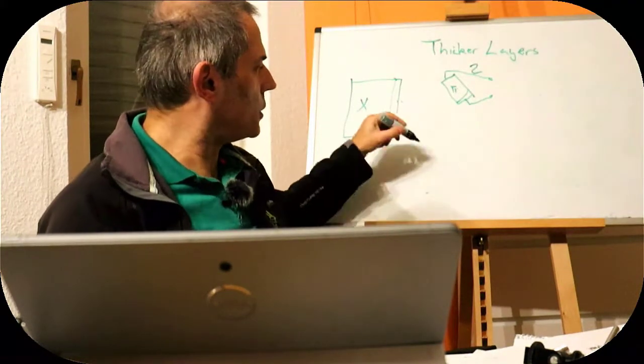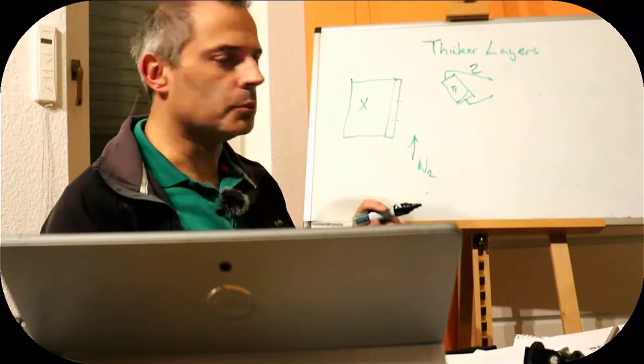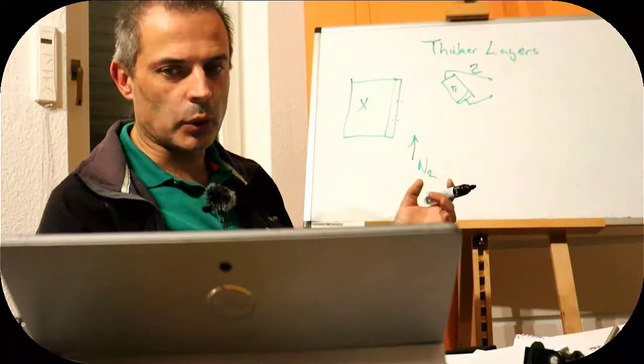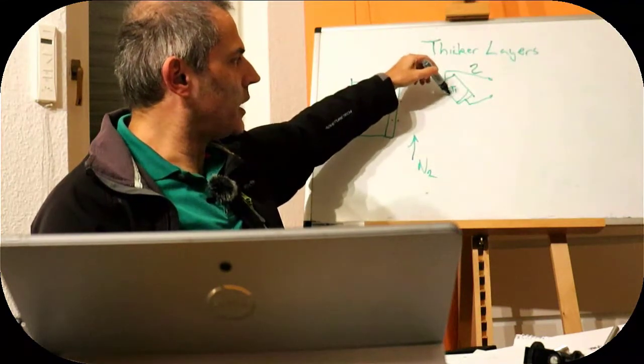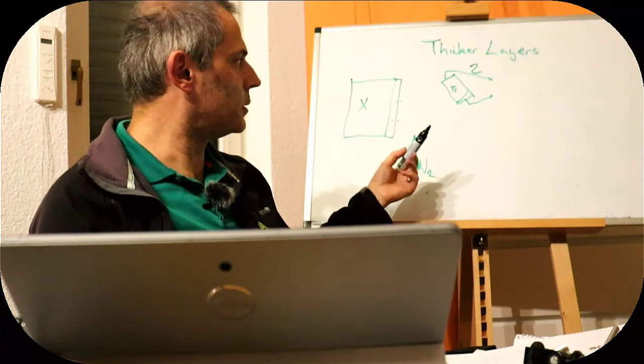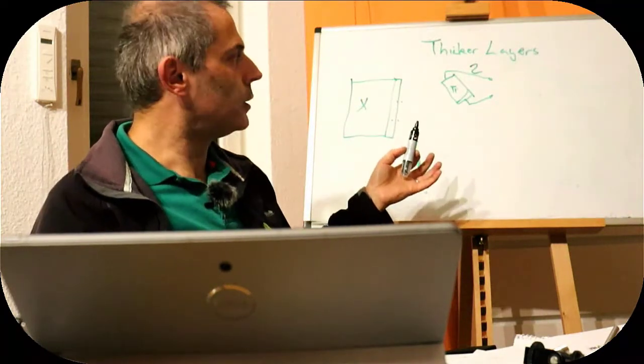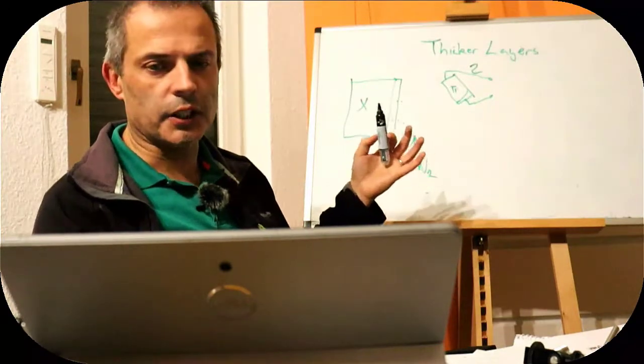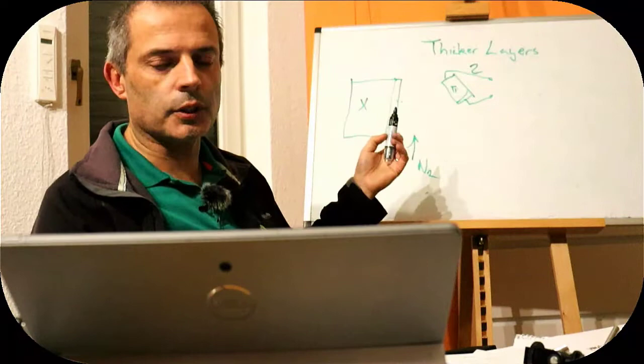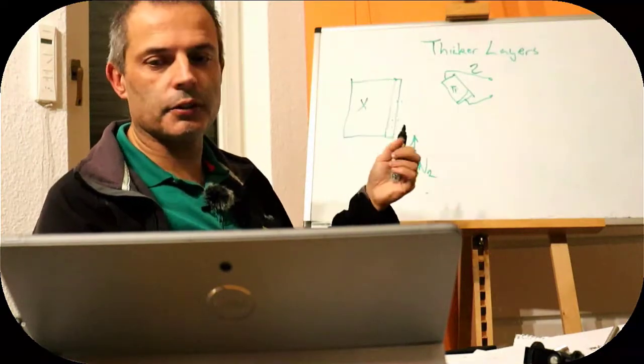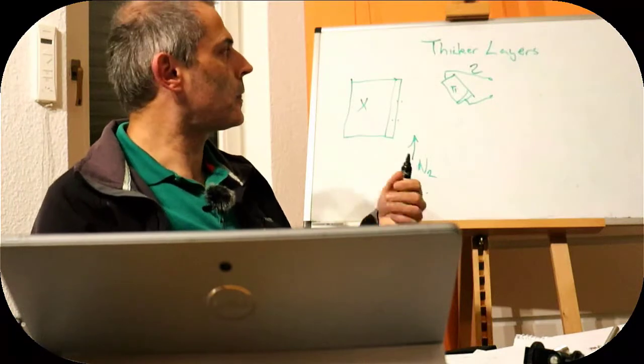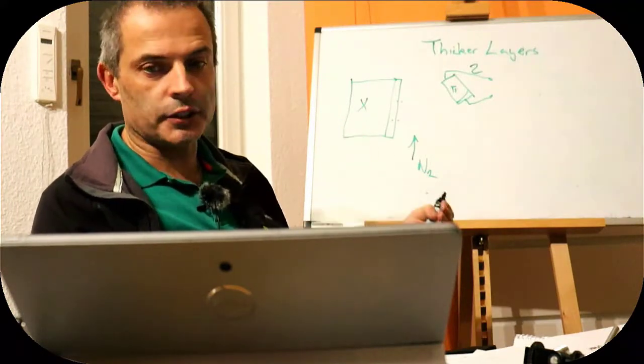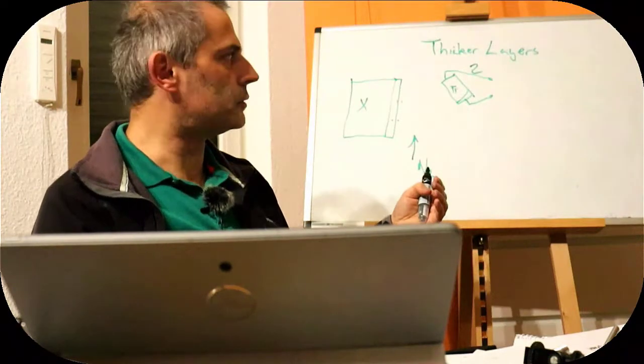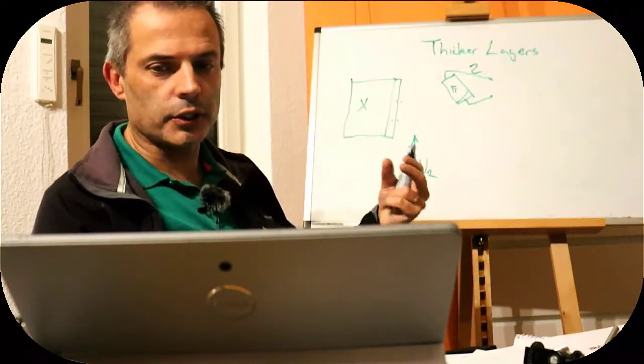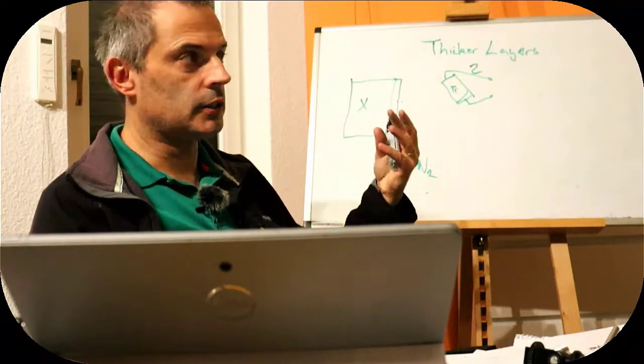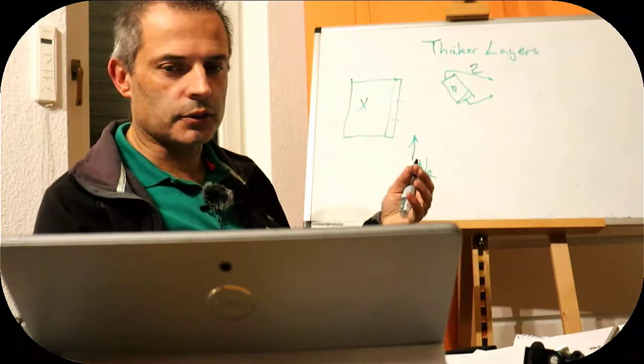If we want to just apply nitrogen, which is what I wanted to do before, it would work, but it wouldn't work very well. Why wouldn't it work very well? The titanium atoms coming along would react with the nitrogen and form titanium nitride, and they would stick to the surface, but we might not get the film that we want, and it might not stick very well. That's because we want the material reaching our surface to have a high enough energy that it bonds to it, and we want it to have compressive stress. The reason we want it to have compressive stress is that if we generate some compressive stress in our film, we can make a better crystal structure, and compressive stress is good against cracks.